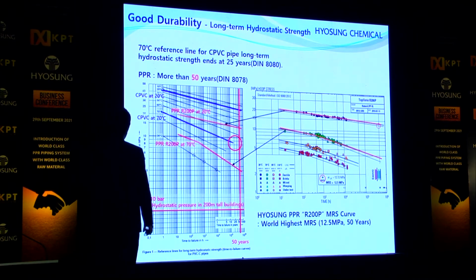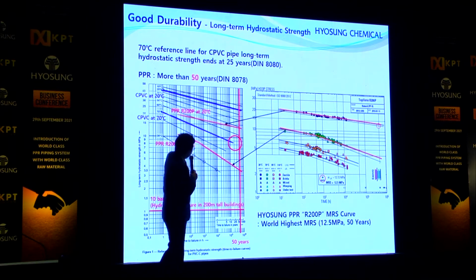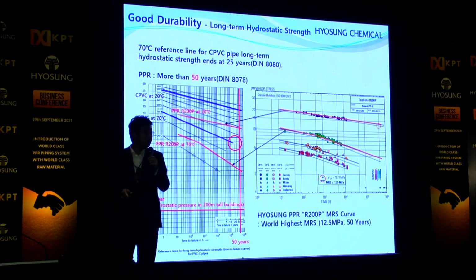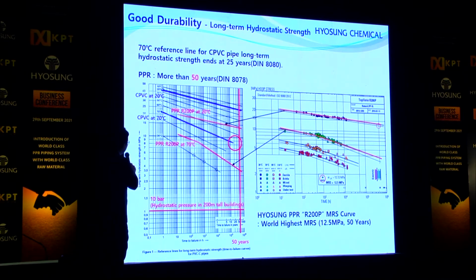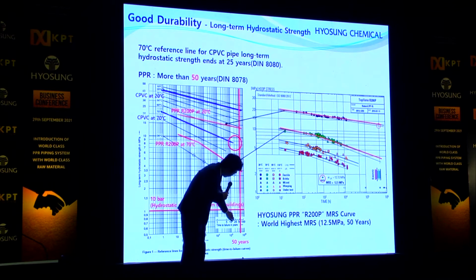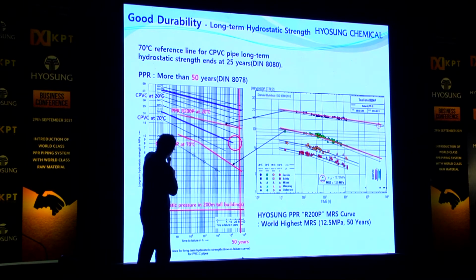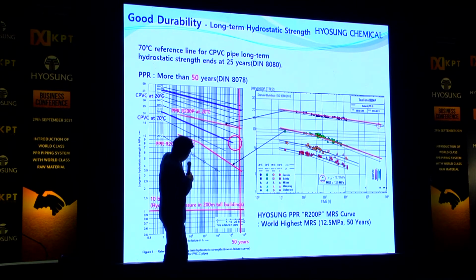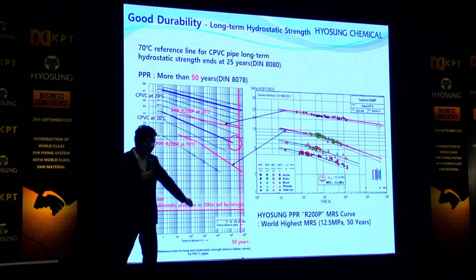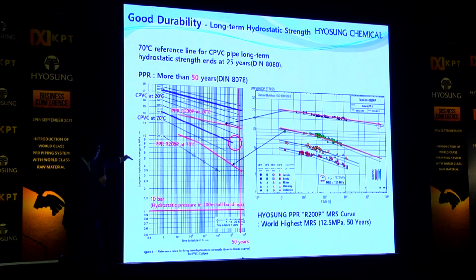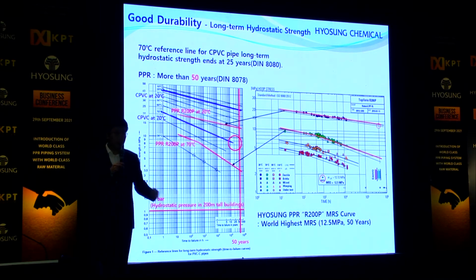This is the graph from the DIN standard. This is mainly the PVC graph. These red lines are our R200P graph. CPVC and PPR are used at higher temperatures. So let's focus on this 70 degrees C, higher temperature. It seems the CPVC graph is at a higher position, but it ends at 25 years. But in the case of PPR R200P, the 70 degrees C graph will last more than 50 years. This is 10 bar, 1 megapascal. So PPR has a little bit lower pressure resistance, but has longer durability at higher temperature compared to CPVC.